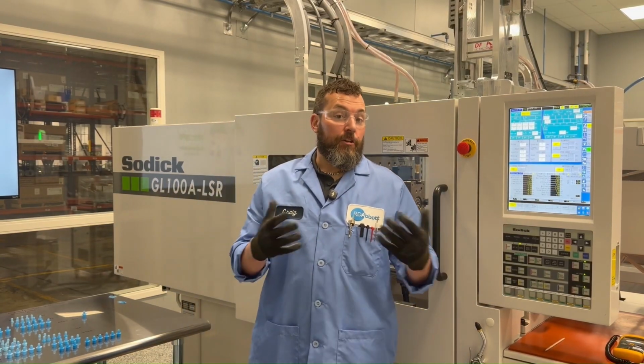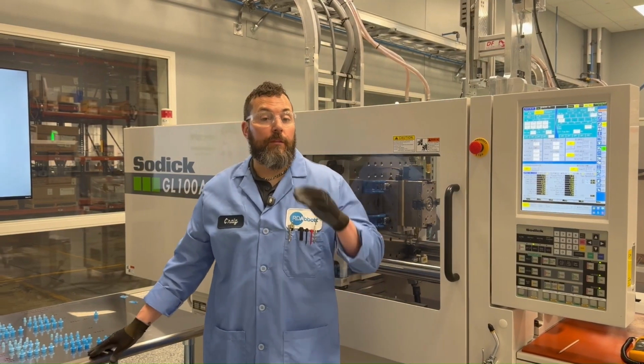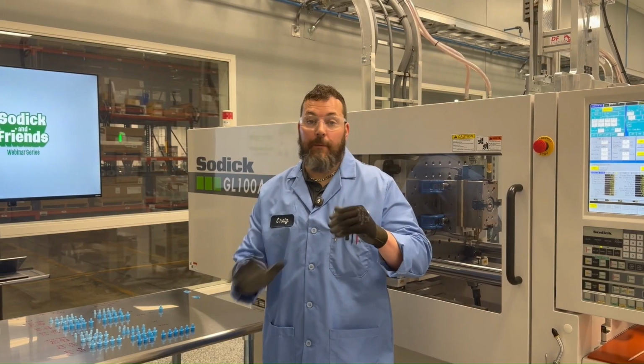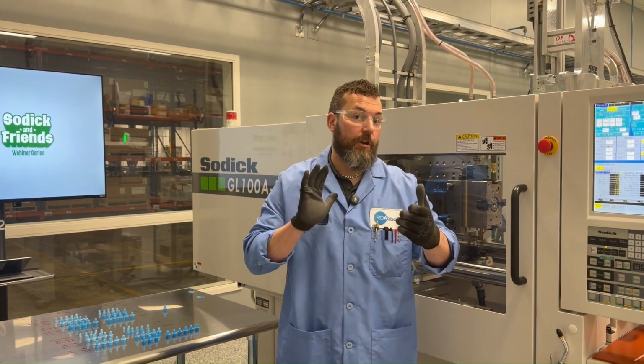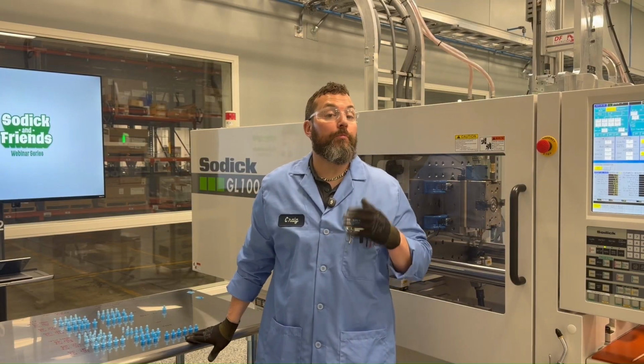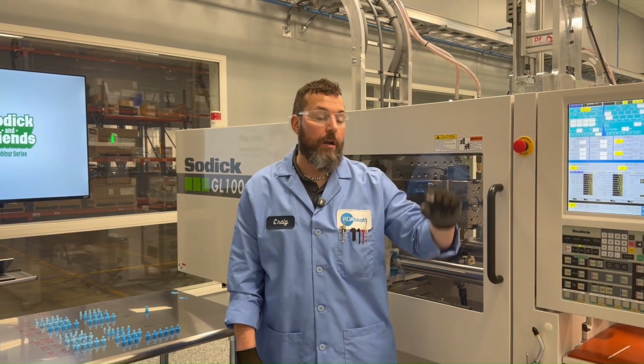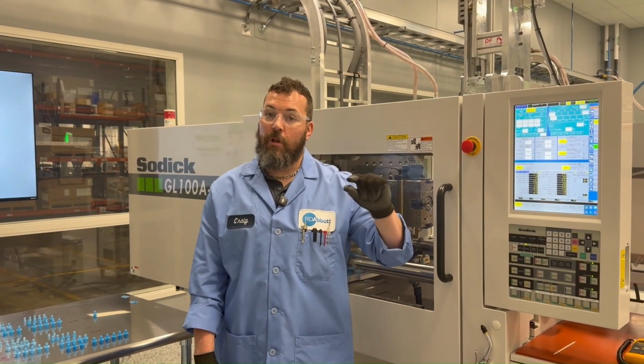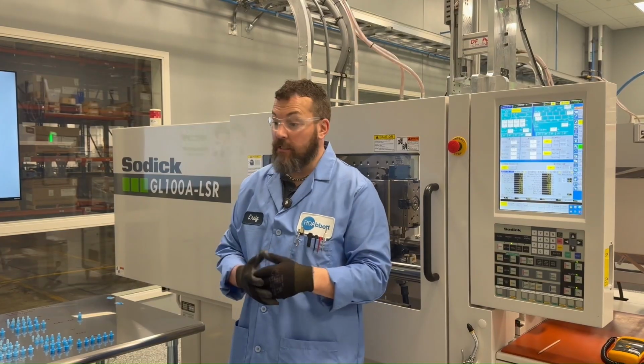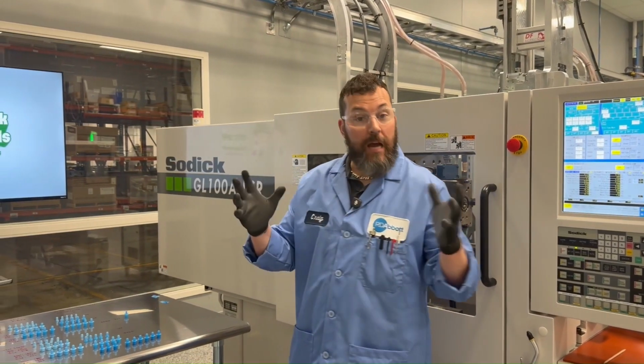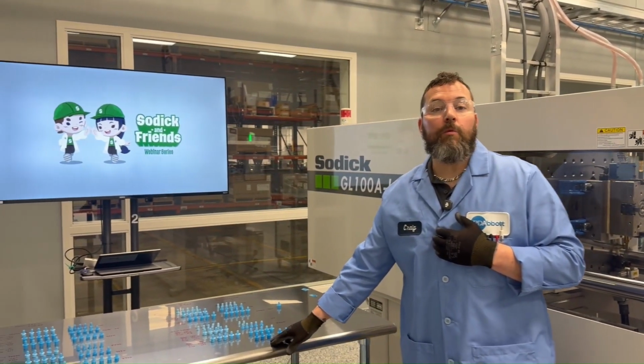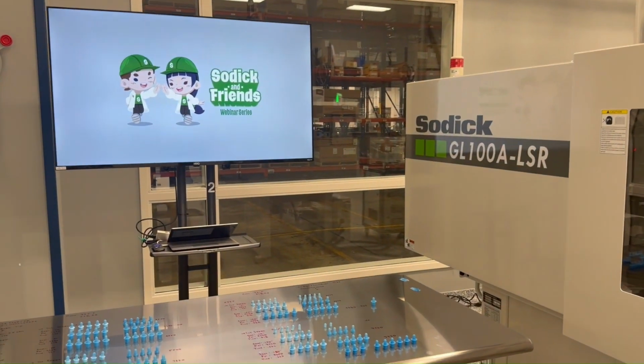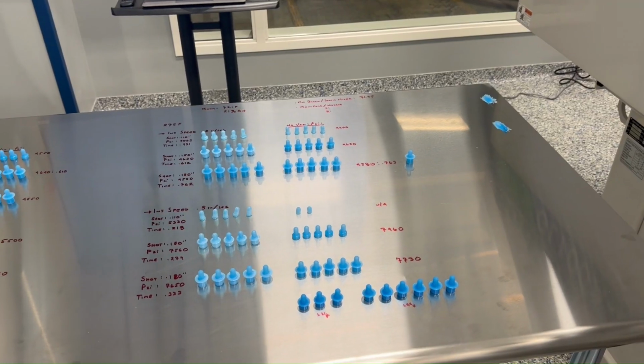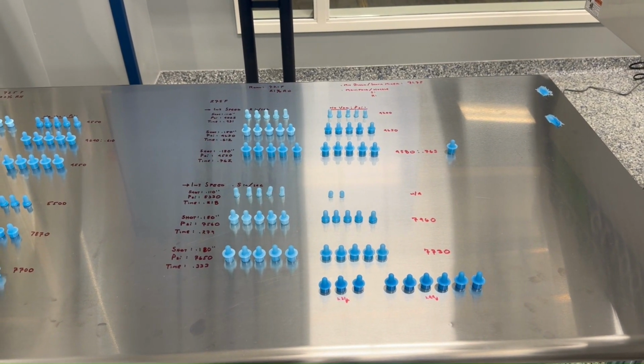From our interval of shots and our changing in process, starting out with 0 hold pressure, 0.2 seconds of hold time. Again, just a little delay so we don't bounce and start to meter immediately. I increased the hold pressure to 500 PSI. Remember, with LSR, small adjustments. We don't want to go too large. Ran 6 shots. That's not the 20 that I said in between, but for time constraints, we were at 1.31 grams on the process that had 0 hold pressure, 1.41 grams consistently on the process that had 500 PSI of hold pressure. Again, single stage, single time.